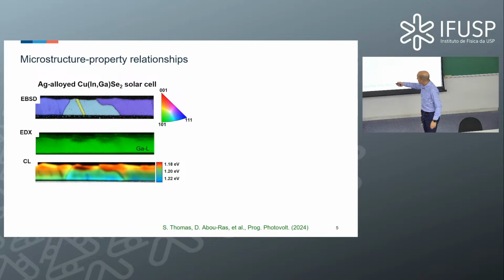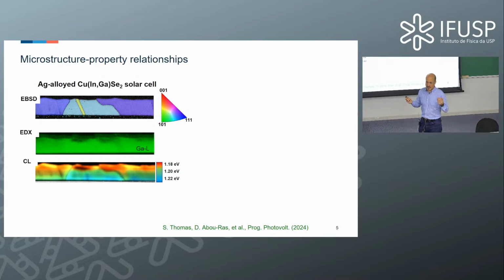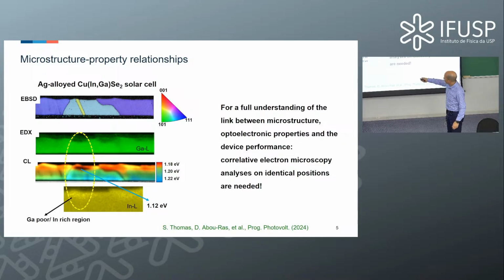And indeed, you can see that this depletion leads to a smaller bandgap energy at the top and a larger one at the bottom. There's also an additional gradient. All of a sudden, what seemed to be very homogeneous and nice is a complete mess from the optoelectronic point of view. And that's what is of interest, because it's an optoelectronic device that we are operating. So the device is not so good, because there's a lot of local variation in the bandgap. You can also check the indium concentration, and you can see where there is less gallium, there is more indium. This fits exactly to what you can already deduce from these other results.